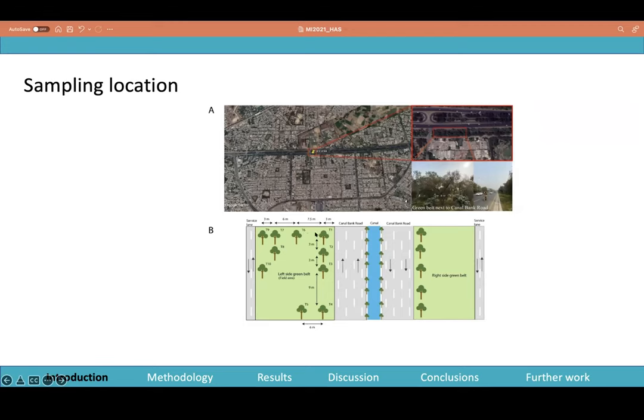The tree leaves were sampled as a function of space and time both. We had tree leaves which were a year old, and we were lucky that the new growing season had started. So we managed to get leaves which were 20 day and 26 day old, and there was no rain in between. Rain can wash off these particulates from the surfaces and can renew more deposition. So that was constant over the freshly grown leaves, but obviously not the 1 year old leaves. And they were also collected with a spatial difference.